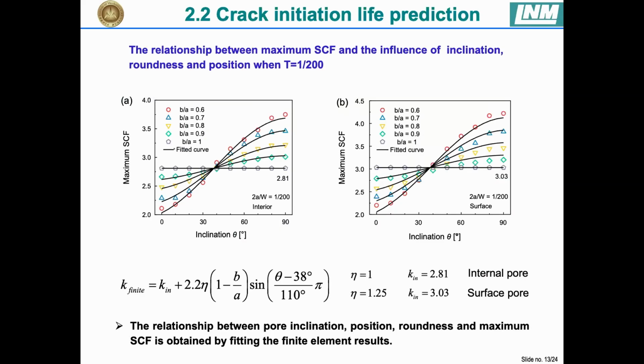Then the relationship between pore inclination, position, roundness, and the maximum stress concentration can be obtained by fitting the results. The obtained equations are listed here for eta equal to 1 and 1.25, corresponding to the internal and the surface pores respectively. And the Kt equals 2.81 and 3.03, corresponding to the internal and the surface circular pores respectively.